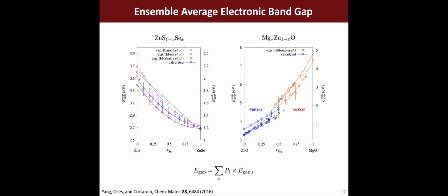Now, there's an important note here. We didn't get to discuss this, but density functional theory tends to underestimate the band gap. So what I did is a rigid shift of the band gap for the calculated results. And you see that if I just shift my axes, I end up getting the relationship very well. I'm not getting the exact values correctly because DFT has problems with the band gap, but this bowing relationship is captured very well by